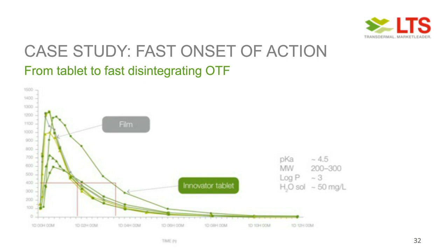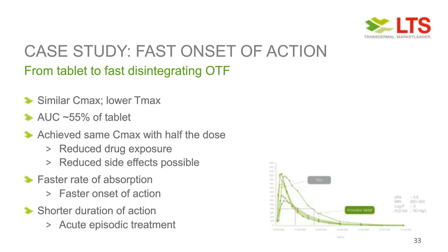In the curve, a PK profile of an API for an episodic treatment, you can see the plasma profile of the innovator tablet compared with several film formulations, especially the gray curve, which is highlighted here. These are different film formulations where we can achieve about the same Cmax as the innovator tablet. And looking at the data and the numbers, we see a similar Cmax, but a reduced Tmax. This was really the target, the aim of the project.